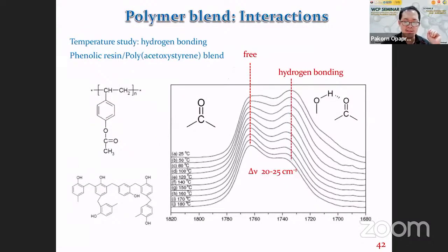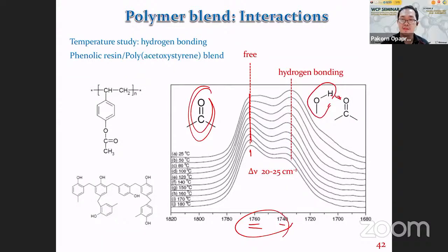Okay. We also can look at the peak of carbonyl group. For example, this carbonyl group is usually located at 1700 something. So free carbonyl group, with no hydrogen bonding, is usually around 1760 wave number. This is free carbonyl. But when we mix OH group, this OH group can form hydrogen bond with the carbonyl. It makes the band shift to lower frequency the same way. But the shift is only around 20 to 25 wave number. This is common for carbonyl group. So as a result, we can look at the intensity of this peak and this peak to tell how much free carbonyl, how much hydrogen bonded carbonyl we have in the system.